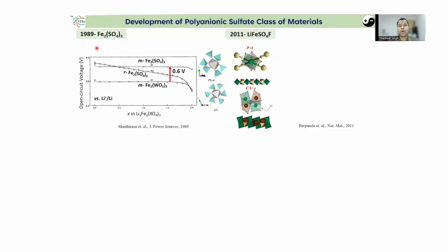Now, the first report of lithium insertion in polyanionic sulfate-based material was in 1989 with the report of lithium insertion in iron sulfate, which also led to the development of the inductive effect theory, where they found that depending on the moieties, whether it's tungsten or sulfate, the voltage of the redox material can be tuned. However, there was a need to increase the redox voltage further, and therefore highly electronegative fluorine atoms were introduced into the system to get this compound, LiFeSO4F.